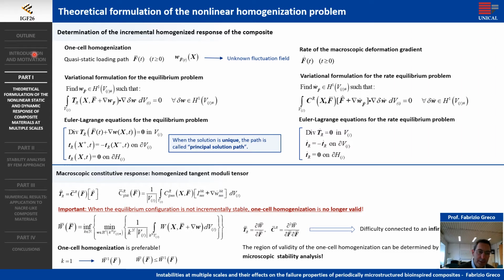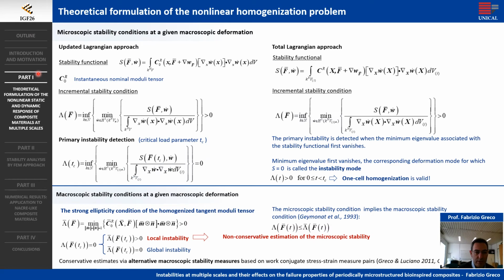Now we are interested in studying the incremental homogenized response of the composite material. The variational formulation and associated equation for the equilibrium problem driven by macroscopic deformation, both the global form and the rate form, are shown here. Once the incremental problem is solved, the macroscopic constitutive response can be defined in terms of the so-called homogenized tangent moduli tensor, which is represented by an overbarred C^R. It is important to note that when the equilibrium configuration of the microstructure is not incrementally stable, the one-cell homogenization approach is no longer valid, and a larger assembly of unit cells must be considered to obtain the homogenized constitutive response.